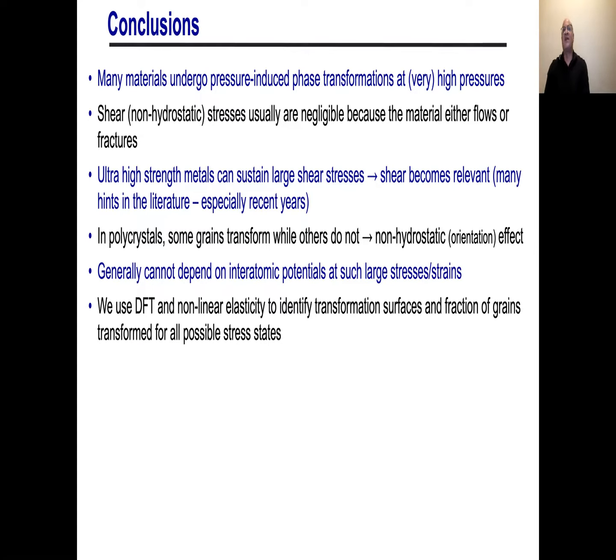Now, you may ask, why didn't I just do molecular dynamics for this instead of DFT and all that elasticity? And the bottom line is most interatomic potentials are not fit to very high strains and very high stresses and multiple high stress phases, like the epsilon phase in iron, for example. So our approach was to use DFT and nonlinear elasticity to identify transformation surfaces and the fractional grains transform for all possible stress states, and then to go back and verify those transformation conditions directly with DFT. So the nonlinear elasticity provides a guidance that makes this calculation much smaller.